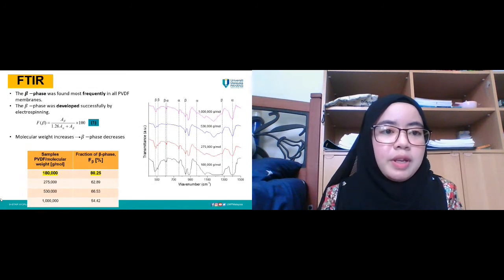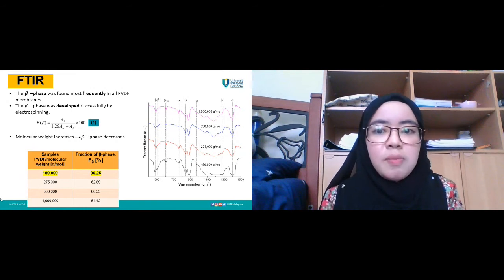Second, based on the FTIR graph, the beta phase was found most frequently in all PVDF membranes. That phase was developed successfully by electrospinning. So from the FTIR data, we can calculate the fraction of beta phase in PVDF by using equation 1. When molecular weight increases, the beta phase decreases.